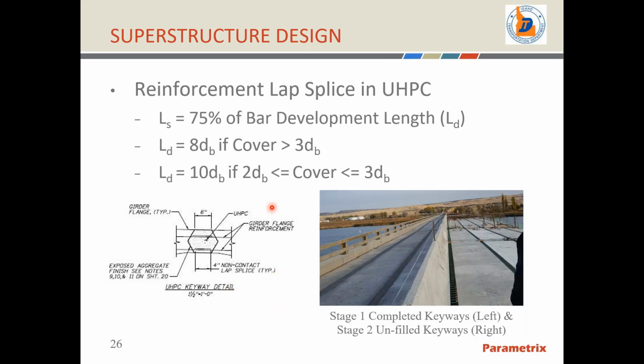So for our particular project, the way we connected our girders together at the keyways is we used a 6-inch wide keyway that accommodated a 4-inch non-contact lap splice. All of the reinforcement in the flange was epoxy coated reinforcement. The top mat were number 5 bars and the bottom mat were number 4 bars.